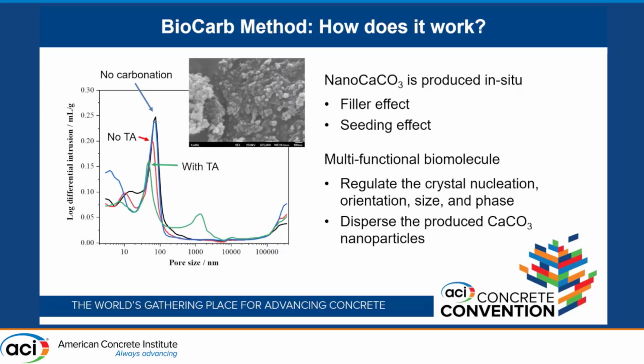Besides that, this is a multifunctional biomolecule. It can also help regulate the crystal nucleation, orientation, size, and phase of the calcium carbonate being precipitated, as well as help with dispersing the produced nanoparticles, which is another challenge we see with nanoparticles. Usually you will have some agglomeration, but with the biomolecule, you're able to disperse them, and that way have a very dense, well-performing matrix.